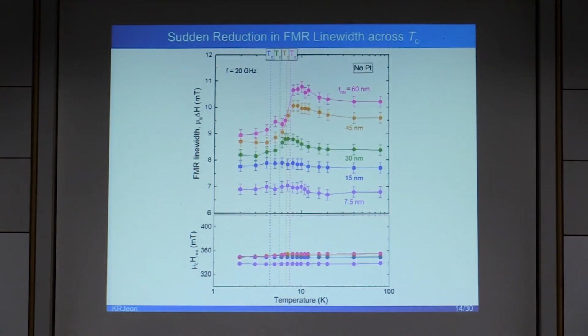This can more readily be seen by plotting the obtained FMR line width as a function of temperature for several different niobium thicknesses. For all niobium thicknesses, the FMR line width increases slightly monotonically with a decrease in the temperature from 100 down to 10 Kelvin. However, when temperature goes down further, a noticeable reduction of FMR line width across Tc, which clearly depends on the niobium thickness, is observed after a slight upturn.